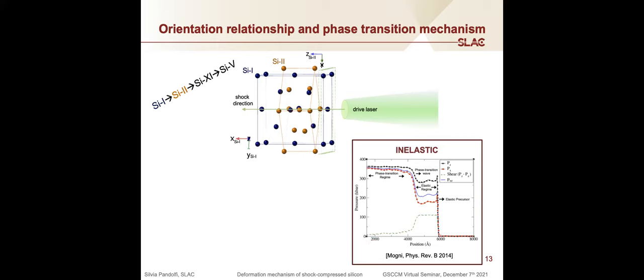So I just want to stress once again that the inelastic deformation in silicon implies that the shear release, so the equilibration between the pressure along and perpendicularly to the shockwave propagation direction, has to happen through the phase transition itself. And so when we think about the transition from the silicon one to the tetragonal silicon two phases, this can happen only for a very specific orientation relationship, which is having the C-axis of this tetragonal phase being parallel to the shockwave propagation. This is because this C-axis is the one along which the interatomic distances are shorter in silicon two with respect to silicon one.